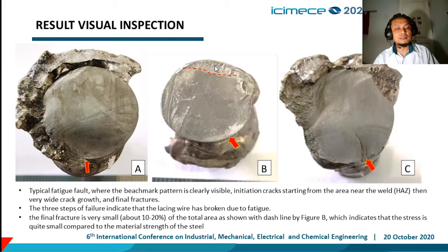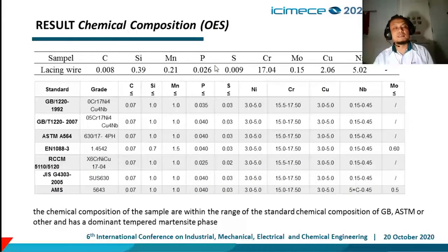The final fracture area is quite small, about 10% of total area, which indicates that the stress is quite small compared to the material strength of steel. This is the result of the chemical composition. The chemical composition of the sample that we can see here is within the range of standard chemical composition of GB and ASTM or other standards.